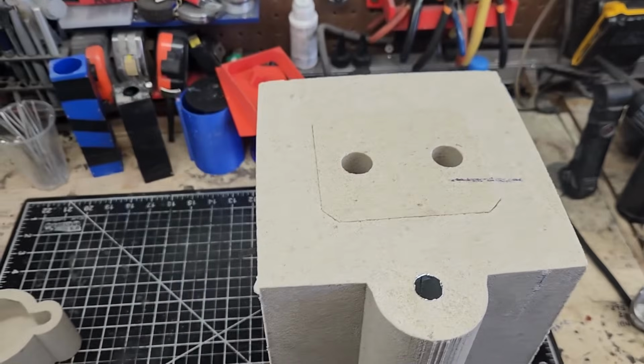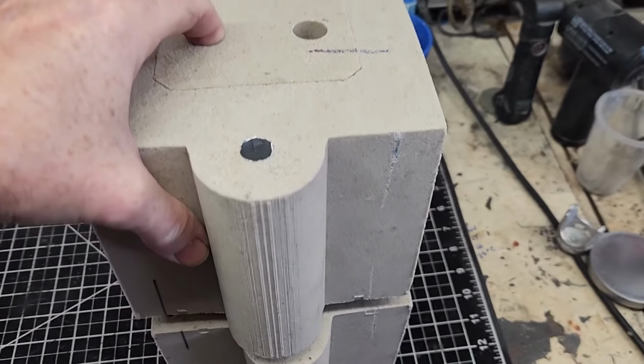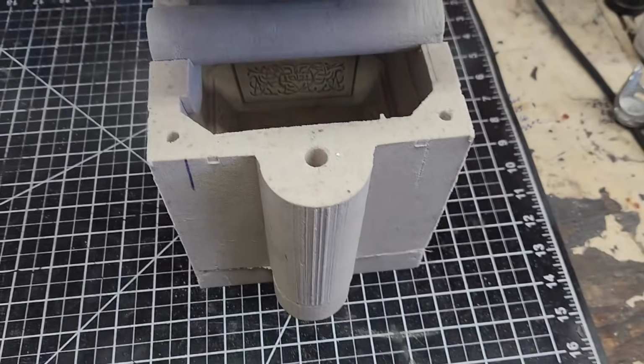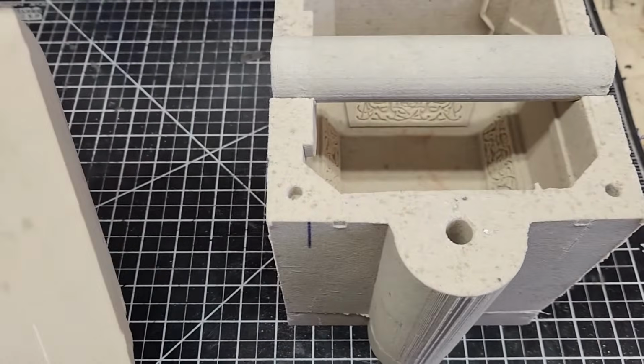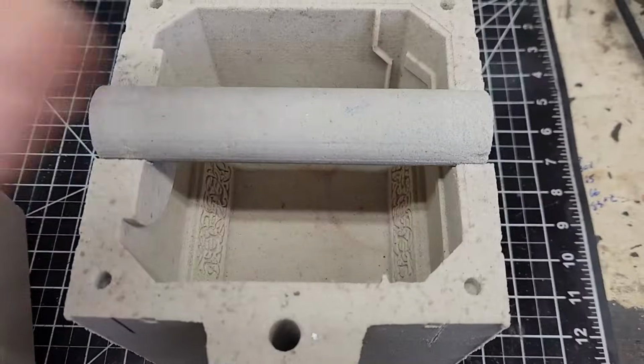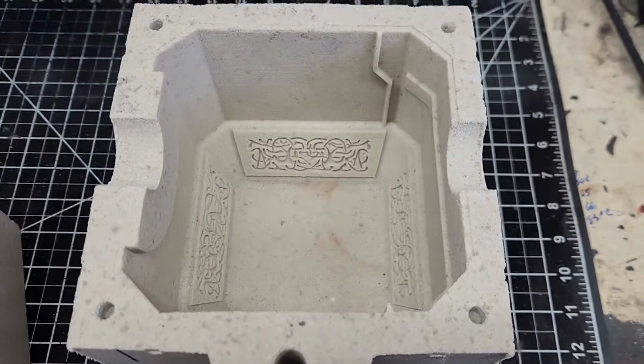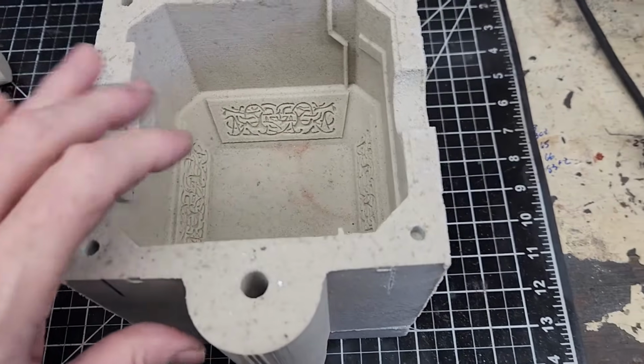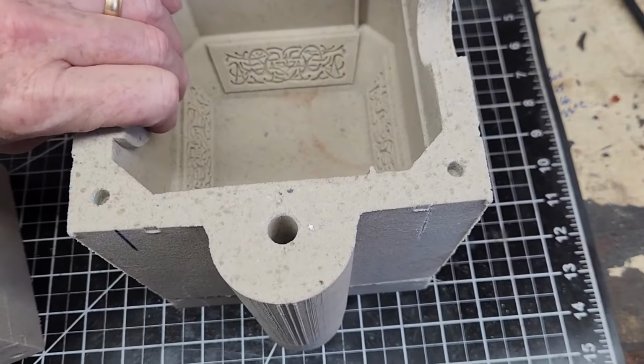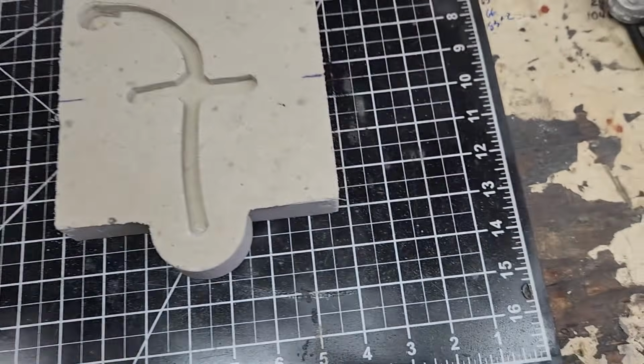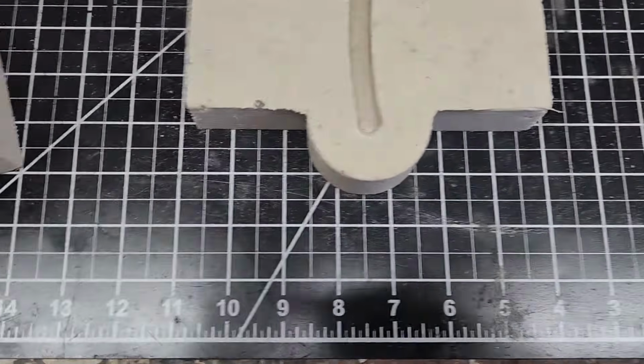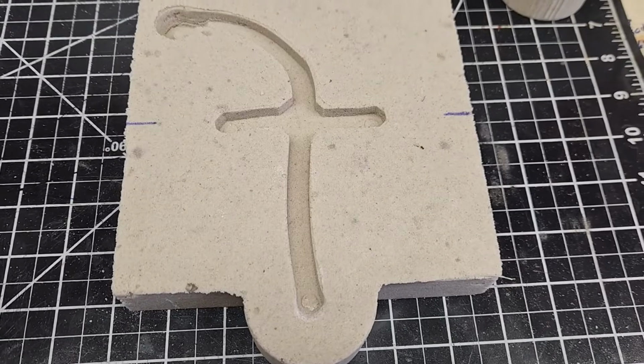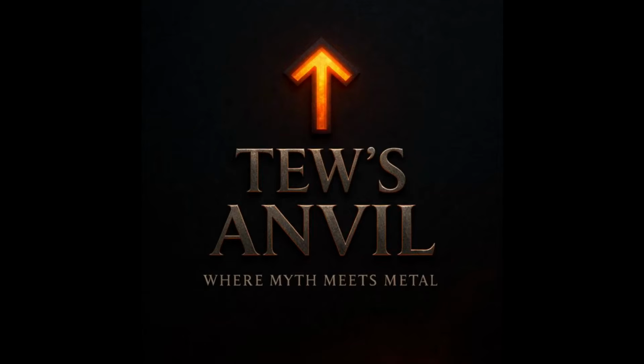When you can pre-warm a mold, hold alignment within a millimeter, and capture complex geometry without erosion or collapse, resin sand isn't faster, cheaper in time, or easier, but it's more capable. And for many of the castings I make today, Petrobond simply wouldn't get me there. If you've looked at a casting and thought, I'll grind that out, resin bonded sand might be worth a closer look.